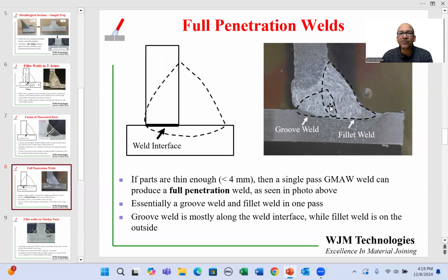So the full penetration weld along the weld interface essentially is a groove weld. And the external weld is a fillet weld. So essentially we have made two welds in one pass. We have made a groove weld and a fillet weld all in one pass. This is also possible, again, if the components are thin enough and you have set the right welding conditions, you can get a full penetration weld.